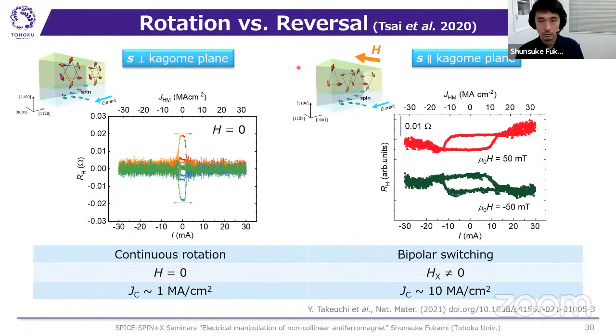And we also studied the chiral spin reversal, which was demonstrated in the very recent Nature papers. So to observe the chiral spin reversal, we applied the magnetic field along the current direction for these configurations. And indeed, we observed the bidirectional switching when we applied the external field. And the switching direction reversed by changing the sign of the external field.